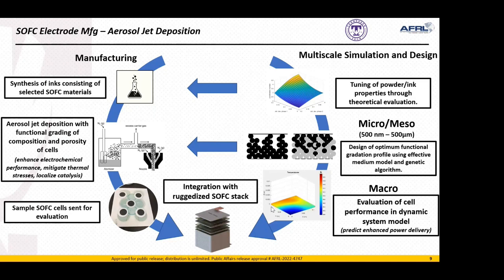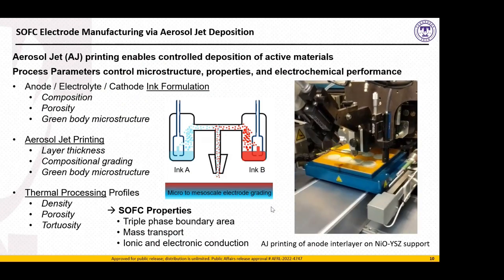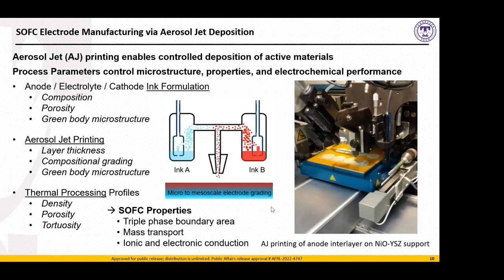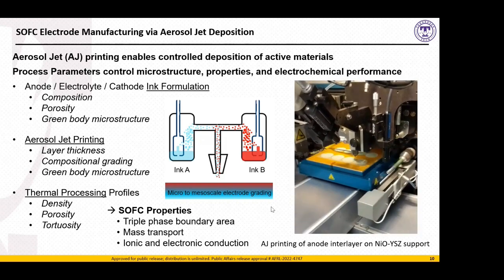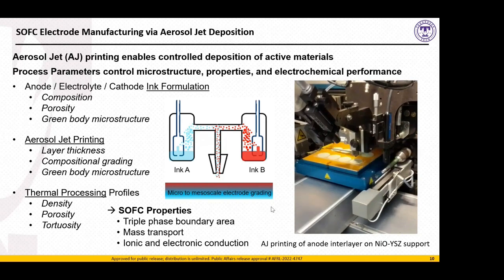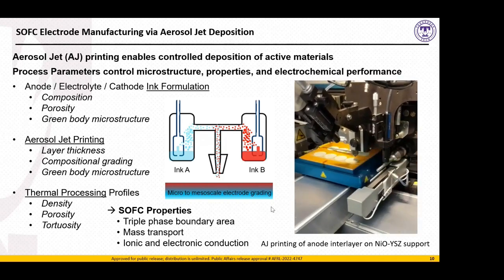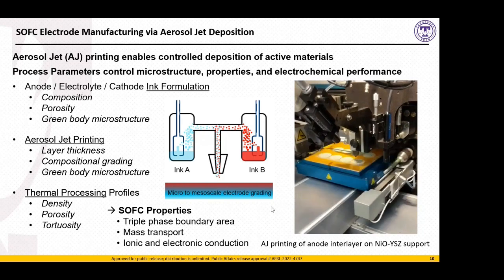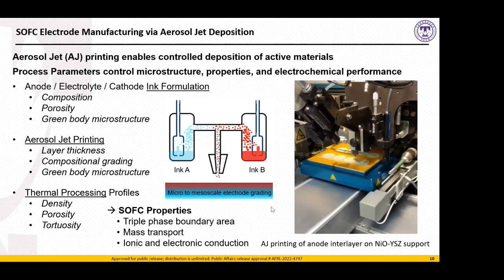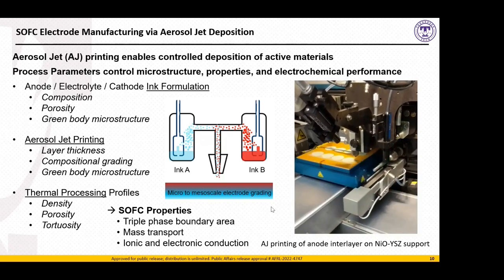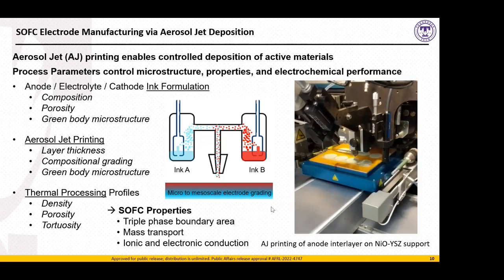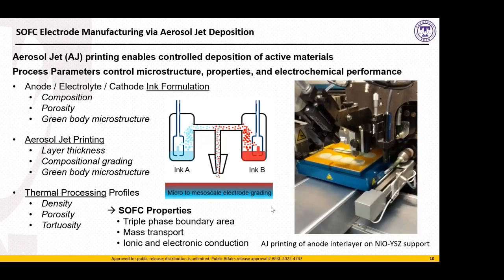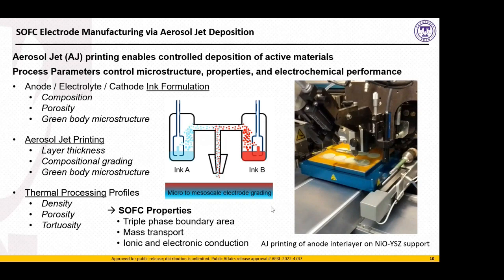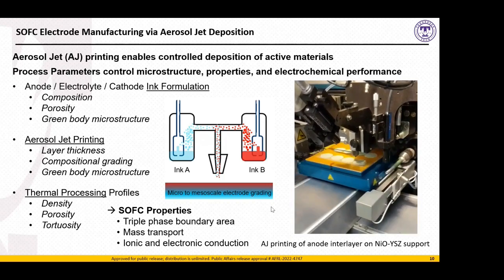The manufacturing method of choice, as we collaborated with the Air Force Research Lab, was an aerosol jet deposition machine. So aerosol jet printing enables a designer to control the deposition of active materials. Many of the process parameters that we used and tuned through our theory lead to the tuning of an ink formulation, a powder formulation by its composition, porosity, and a green body microstructure.